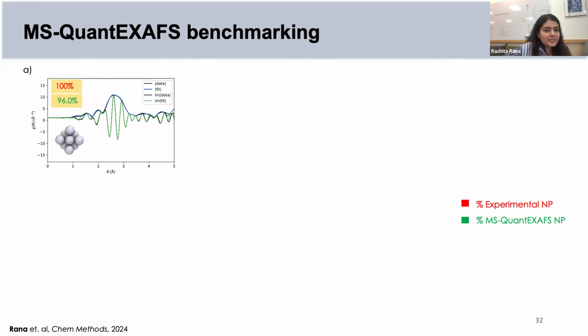And the idea was we were doing palladium on magnesium oxide, and we were trying to understand how calcination treatment was impacting the dispersion or fragmentation of palladium, and more importantly, how this palladium site was behaving for the ethylene hydrogenation reaction. So we had two different calcination temperatures. One was 500, and the other was 700.